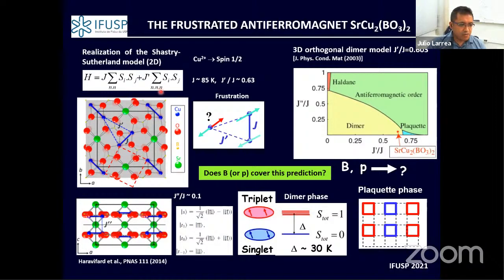To explain this kind of model: the material has a tetragonal crystal structure. Here we see a projection on the A-B plane, while perpendicular to this plane is the C direction, shown in the lower panel. So you have layers peeling up or peeling down along the C direction.